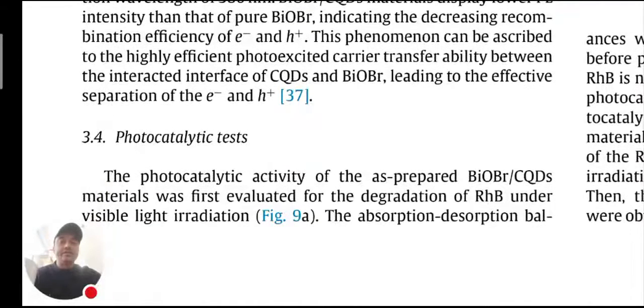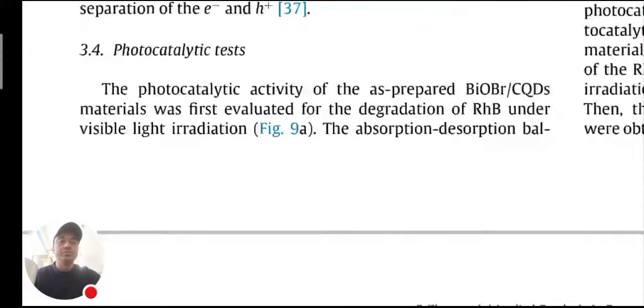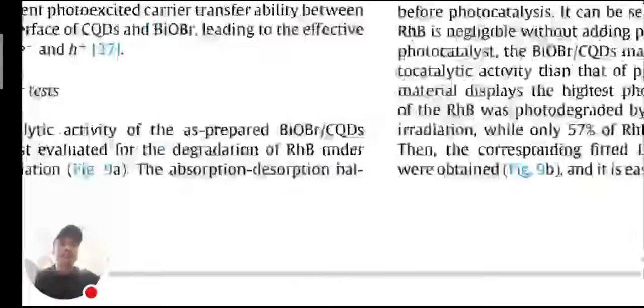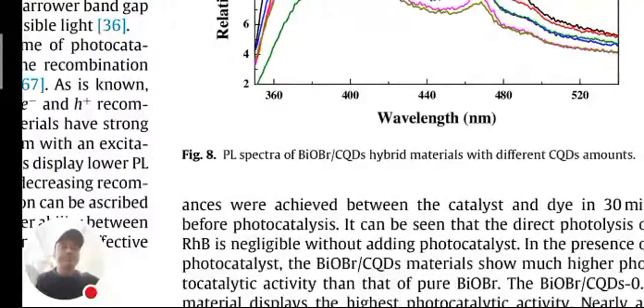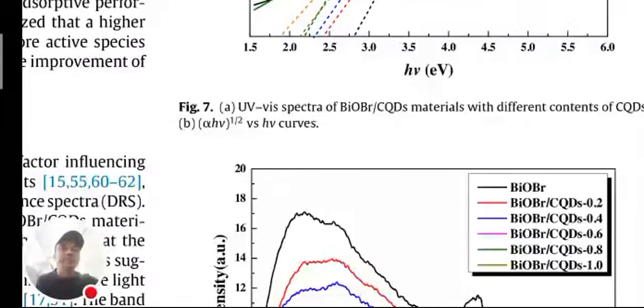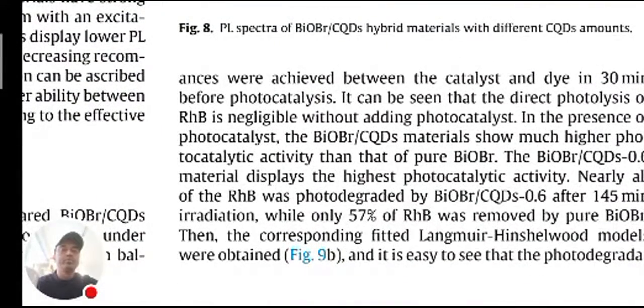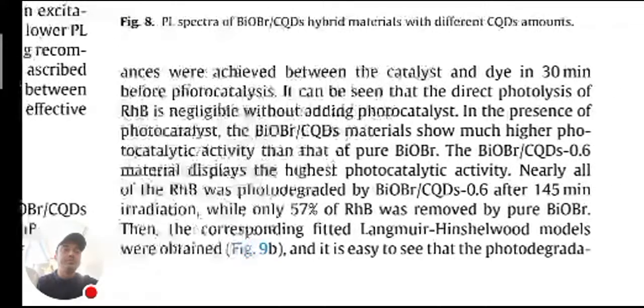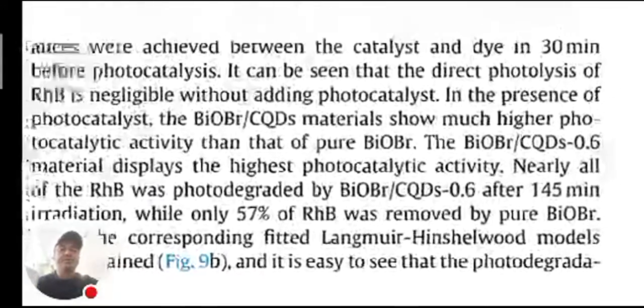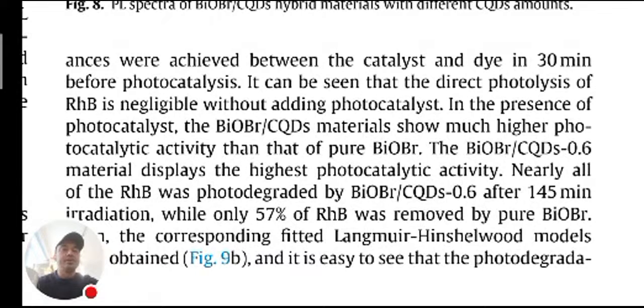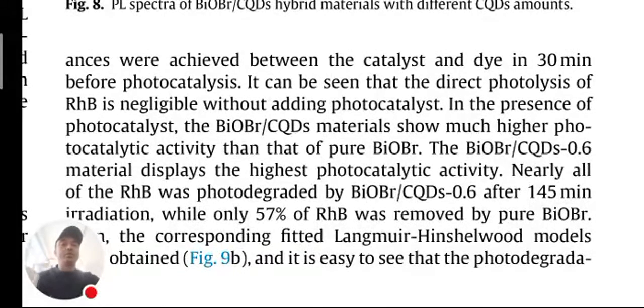Photocatalytic test. The photocatalytic performance of the as-prepared BiOBr carbon quantum dot material was first evaluated by the degradation of rhodamine B under visible light irradiation, after adsorption and desorption. Adsorption equilibrium was achieved between the catalyst and the dye in 30 minutes before photocatalysis. Direct photolysis of rhodamine B is negligible without adding photocatalyst.